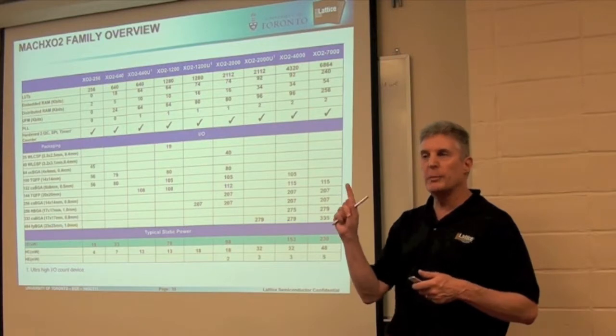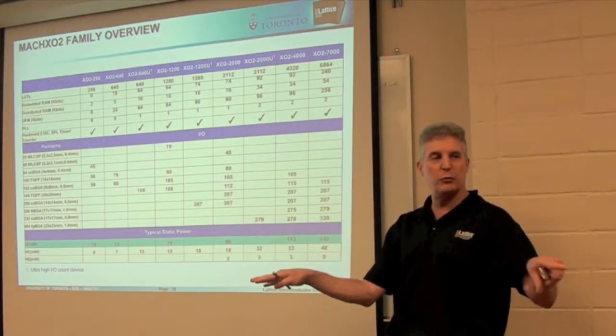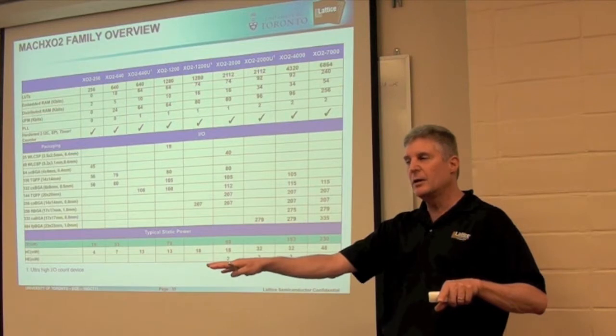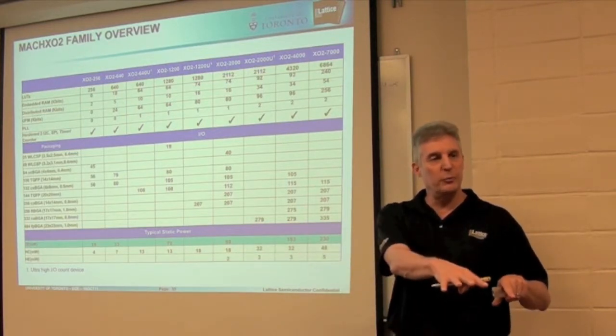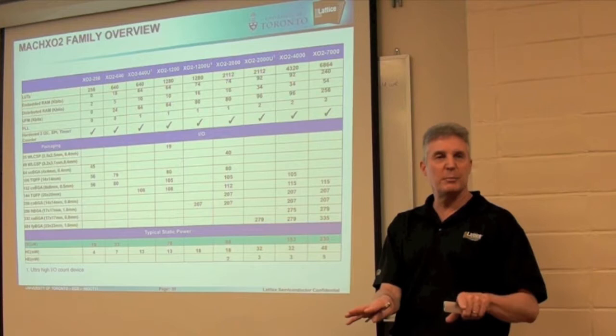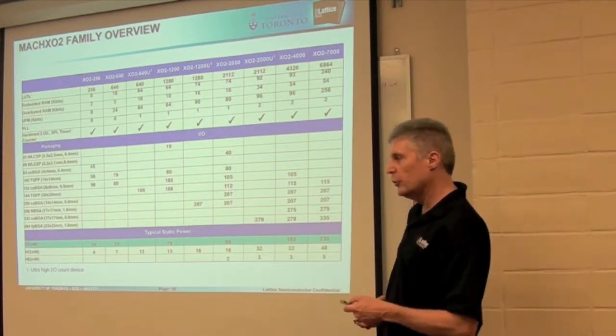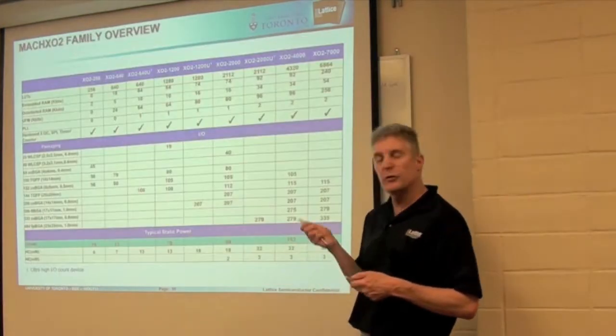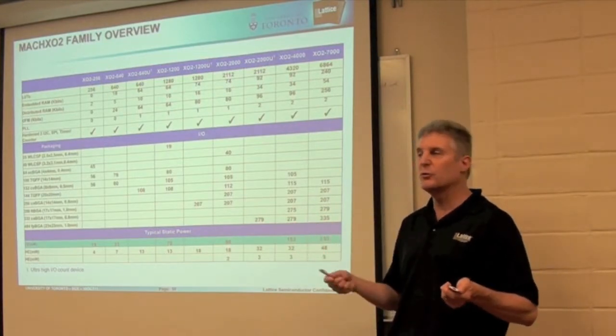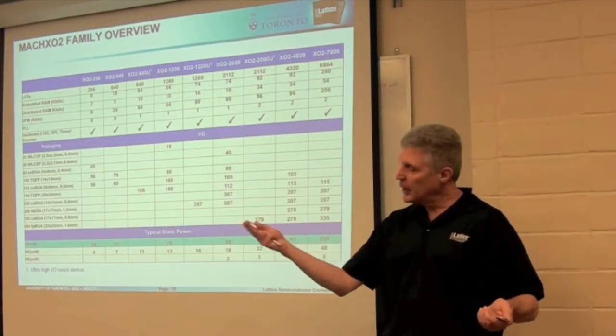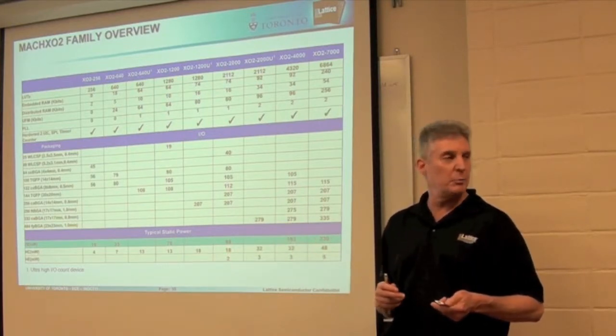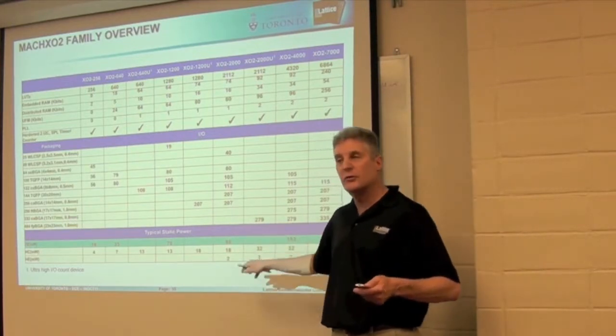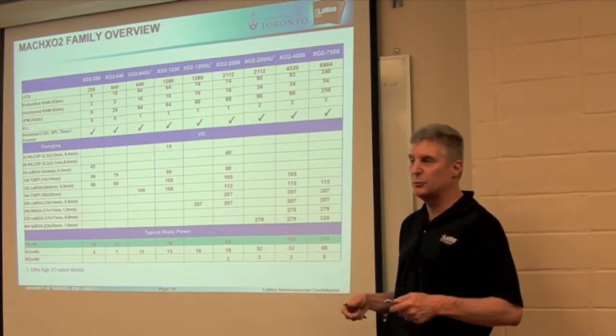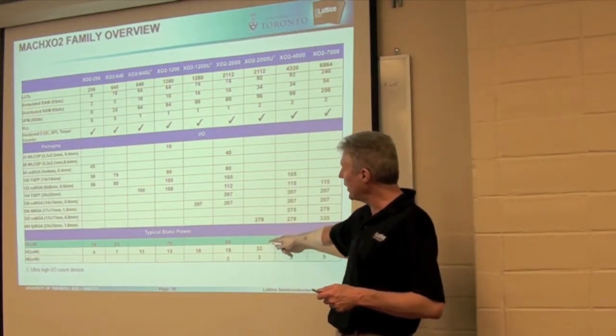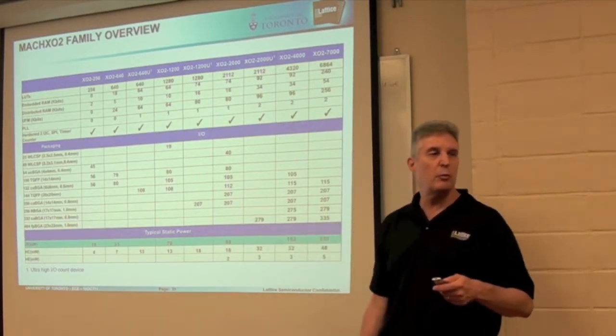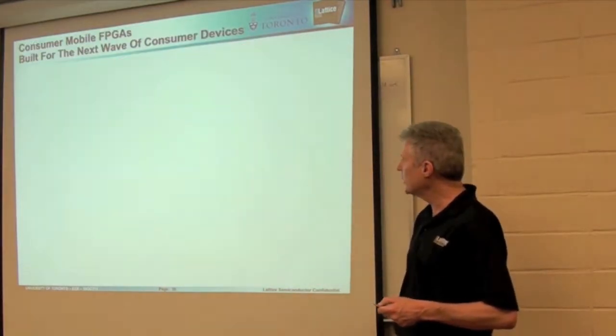So we actually built one mask set that can be processed in the fab with two different threshold voltage implants and get a high speed, higher power option, or a low speed, very low power option without touching the mask set and without making a new design. The reason we do this is because there are different application markets. Some customers care more about the speed than the power. They say, I need twice the speed and I'm willing to pay a milliwatt in power. Even at 2 or 3 milliwatts, these are very, very low power parts relative to classic FPGAs. But if you want to really operate in the handheld market, you've got to have the microwatt power level. So we implemented that as well.